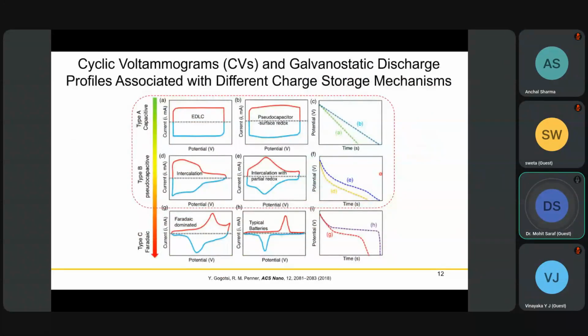Again, it's a quick comparison of how cyclic voltammograms and galvanostatic charge-discharge profiles vary with different processes. I will explain what these CVs and GCDs are in my next few slides. But as a first indication, when you see any carbon material's current response in the cyclic voltammogram, you will see a typical rectangular shape, and of course the discharge profile will be basically a straight line with constant slope, no curvature.